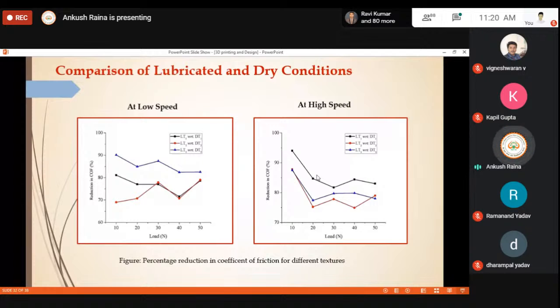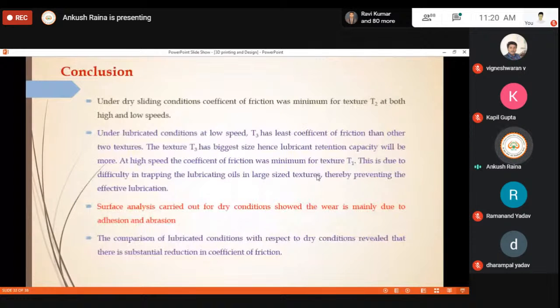So under dry sliding conditions, the coefficient of friction was minimum for texture T2 at both high speeds and low speeds as obtained. But under lubricated conditions, at low speeds, T3 has the least coefficient of friction as told to you. The texture T3 has a bigger size, has more lubrication capabilities, as has been discussed previously. But whereas in case of high speeds, the coefficient of friction was minimum for the texture T1. This is due to the difficulty of trapping the lubricant. Again, the lubrication retention capability was less, which prevented the effective lubrication for the large size textures.